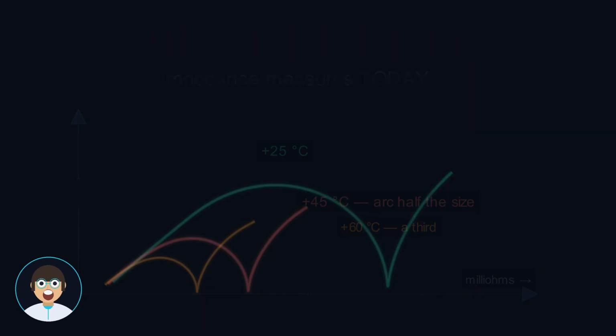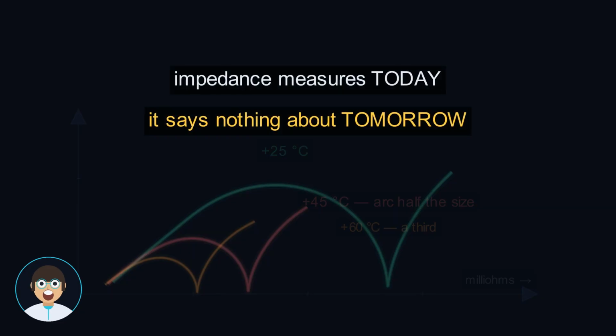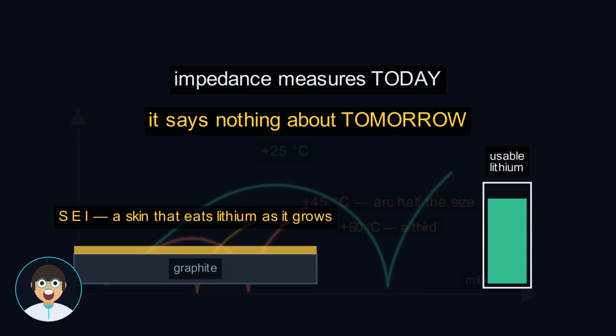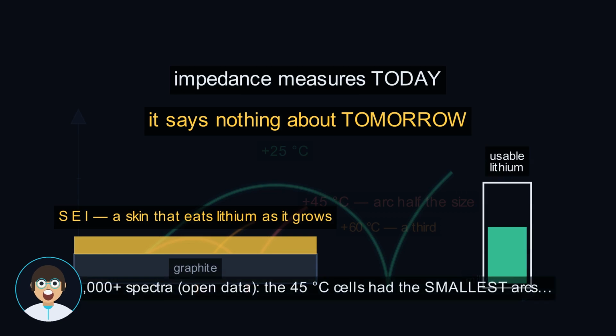Because impedance only measures how easily charge moves today. It says nothing about tomorrow. Inside the hot cell, the side reactions obey the very same Arrhenius law, and they speed up too. The protective skin on the graphite, the SEI, a rust-like film that eats a little lithium as it grows, thickens faster and faster. In a famous open dataset, the cells cycled at 45 degrees showed the smallest, prettiest arcs, and